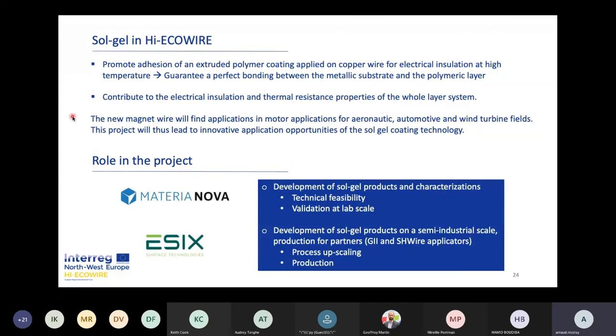It's important to note here that compared to classical organic varnishes, sol gel coatings show higher thermal resistance and an excellent adhesion on a large number of substrate materials. Moreover, thanks to their dielectric properties, sol gel coatings can be used for electrical insulation. This property is linked to the coating thickness. There is indeed proportionality between breakdown potential and thickness.